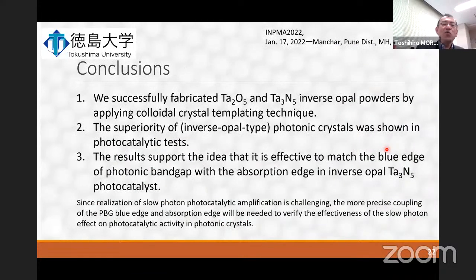Okay, so we conclude our result as follows. We successfully fabricated tantalum oxide and tantalum nitride inverse opal powders by applying the colloidal crystal templating technique. The superiority of the photonic crystal was shown in the photocatalyst test, you see. And the results support the idea that it is effective to match the blue edge of the photonic band gap with the absorption edge in inverse opal tantalum nitride photocatalyst.